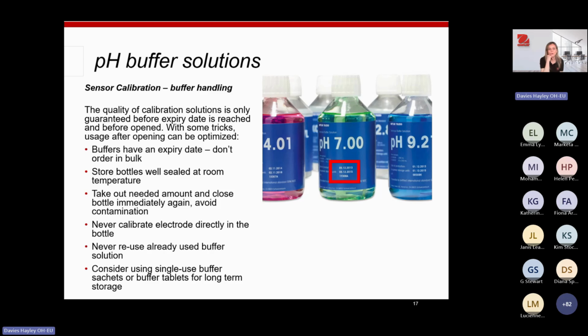For the pH solutions, we are owned by Mettler Toledo, so we have our own range of very expensive pH buffers. They should only be used when you are purchasing them ready to use off the shelf. The pH buffers are only guaranteed before the expiry date is reached, so make sure you're not using any pH buffers after the printed expiry date on the label. Don't order in bulk if you are ordering ready-made ones. Store bottles well sealed at room temperature. Only take out the amount needed from the bottle and then close the bottle again to avoid any contamination.